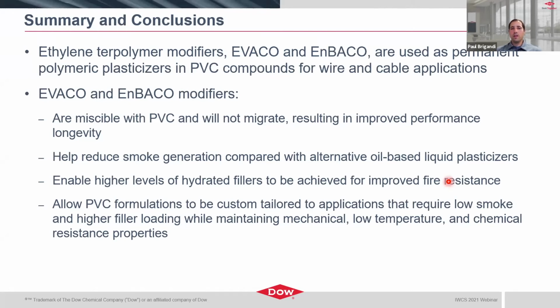They help reduce smoke generation when used in various compositions, either as an alternative to the liquid-based plasticizers or in combination with. They enable higher level of filler incorporation so that you can tailor your fire performance, whether it be improved or reduced smoke, much better flame propagation, et cetera. And they really allow the formulations to be custom tailored to any given application, whether it's a need for improved mechanicals, low temperature, or more importantly, again, the fire resistance.